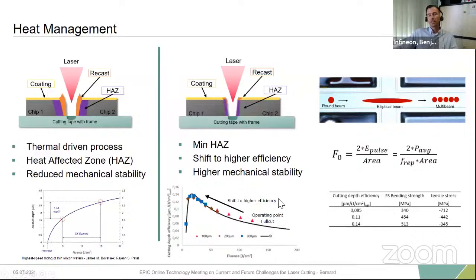But here I did an easy trick. I used the DFL 7562, a commercially available platform from Disco, where you have the nice possibility to change the length of your elliptical beam. So I configured 3 different lengths and the rest I left unchanged. And as you can see, I could come closer to the highest cutting efficiency by changing the length. This then did lead to a higher die strength and also to less tensile stress that we have in the sidewall.